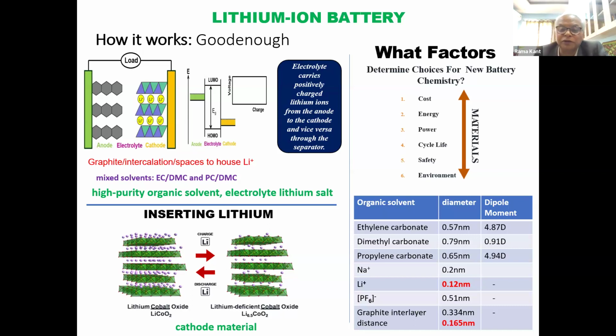So the components involved in a lithium-ion battery are ethylene carbonate, dimethyl carbonate. These are solvents, propylene carbonate. You can see their size is like a fraction of a nanometer. But how do you decide this system? Because when you say interlayer graphite, the distance between interlayers, from center of carbon to carbon, is 0.334 nanometer. But if you just exclude the carbon portion, only the gap portion, that is 0.165. So lithium is smaller than this, so it can freely move inside these spaces.